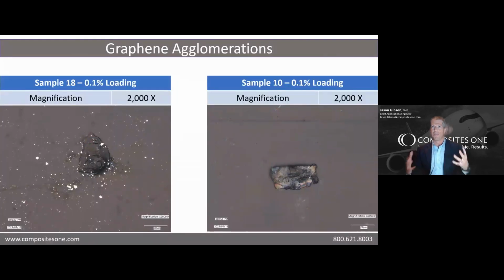Now, we also want to do a little bit of an analysis. So let's take a look at some of that. One thing to keep in mind is that all samples had some form of agglomerations of graphene in them. These agglomerations are where the graphene did not get fully dispersed into the resin. While all samples had some form of agglomerations, each sample had varying levels of this. Now, theoretically, the better dispersed the graphene is in the matrix, the better its performance.